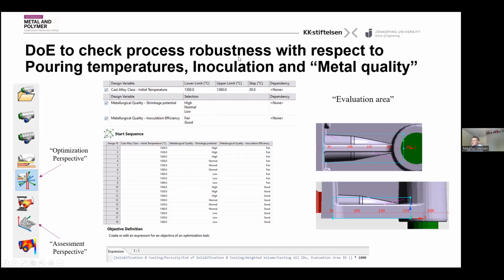But then there are other things which can happen in processes as well. Certain days you have a worse metal quality. If you have more oxides, for instance dross and slags, those can nucleate porosities. So that means that your shrinkage tendency gets higher. And in Magma, we have something called the shrinkage potential factor, which accounts for this, without explaining the details. So you can easily say, what happens if I go away from the normal setting to high and then low, and see how that would affect the situation. Also, the inoculation, which is done to promote the graphite formation, will affect the shrinkage. It's another factor which is quite important. You can then easily add that too.